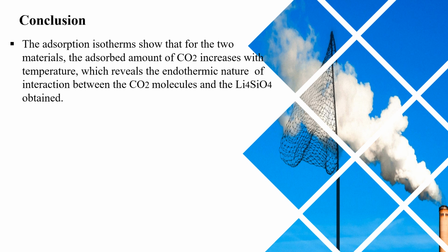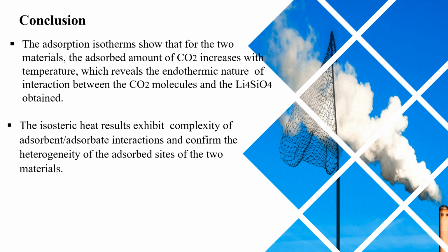Conclusion: the adsorption isotherms show that for the two materials, the adsorbed amount of CO2 increases with temperature, which reveals the endothermic nature of interaction between the CO2 molecules and the lithium silicate obtained. The isosteric heat results exhibit complexity of adsorbent-adsorbate interactions and confirm the heterogeneity of the adsorption sites of the two materials.